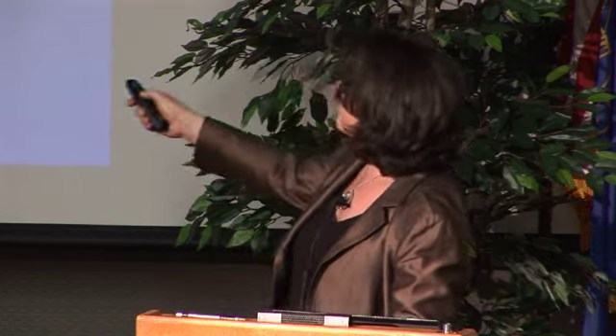What we've actually done is taken the cell apart and discovered that because these cells go slowly, the rate capabilities for lithium-air are pretty pathetic. We have a totally fuzzy white metallic lithium negative electrode at the end. And so what we've done is we've taken the lithium out and we've put fresh lithium in, and we can keep going for another few cycles. So the problem really is protecting the negative electrode.